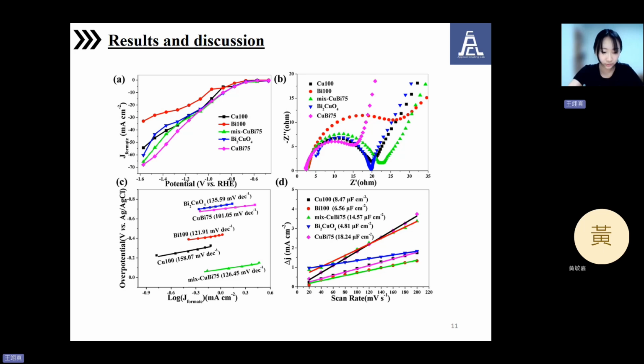Altogether, these results confirm that the MOF-derived CuBi75 catalyst achieves its excellent performance thanks to a combination of efficient charge transport, higher surface area, and favorable reaction kinetics, primarily enabled by the formation of a Bi2CuO4 interface structure.